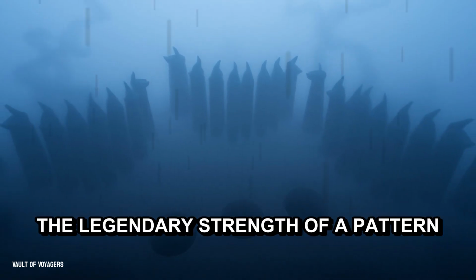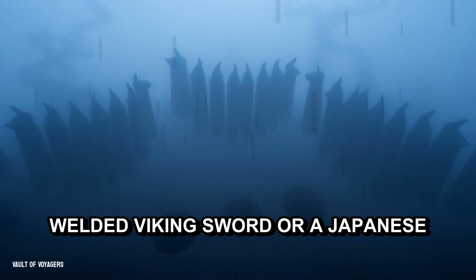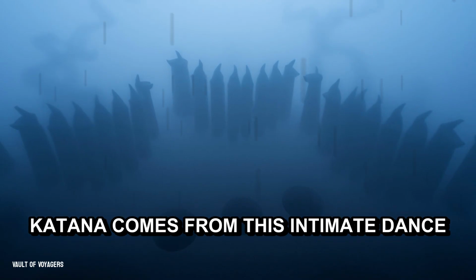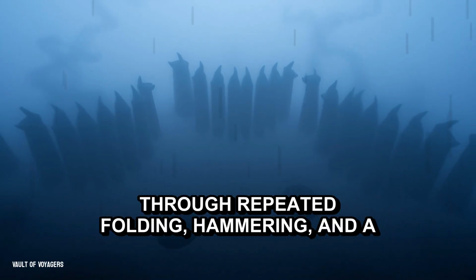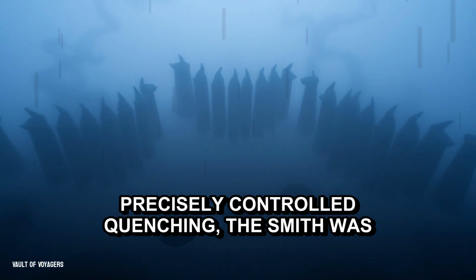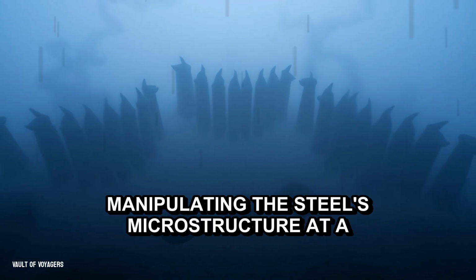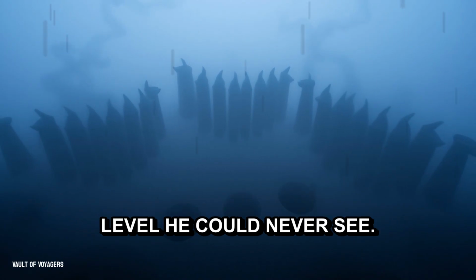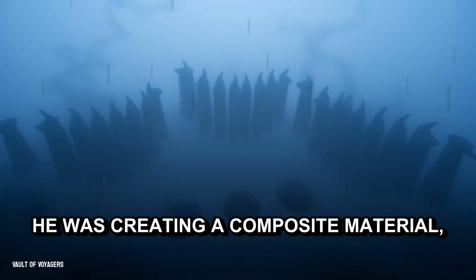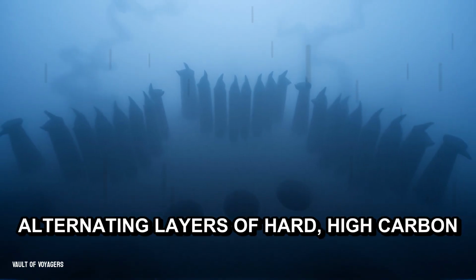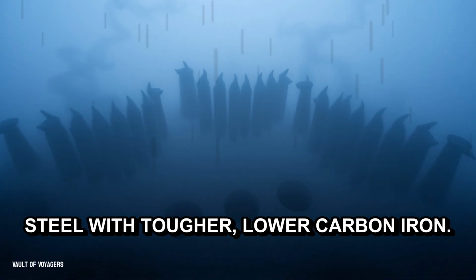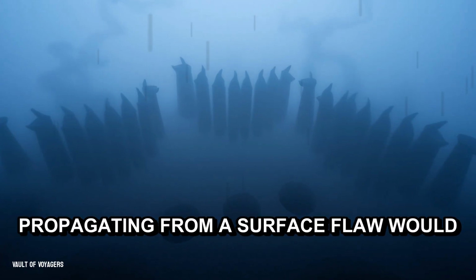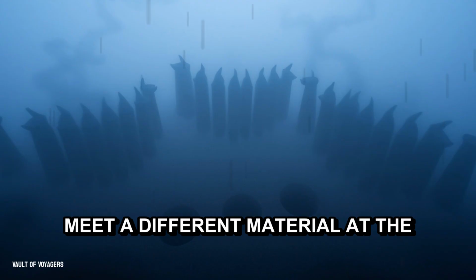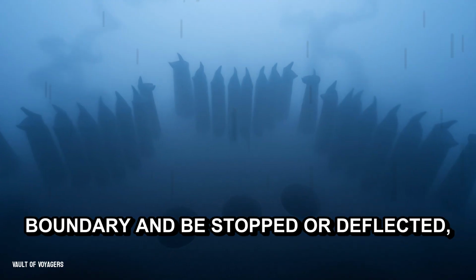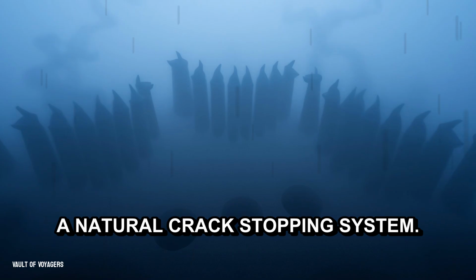The legendary strength of a pattern-welded Viking sword or a Japanese katana comes from this intimate dance with carbon. Through repeated folding, hammering, and a precisely controlled quenching, the smith was manipulating the steel's microstructure at a level he could never see. He was creating a composite material, alternating layers of hard, high-carbon steel with tougher, lower-carbon iron. This lamination meant that a crack propagating from a surface flaw would meet a different material at the boundary and be stopped or deflected, a natural crack-stopping system.